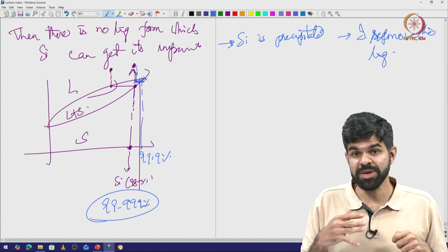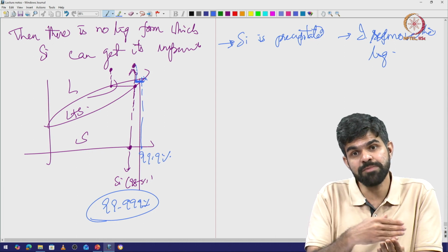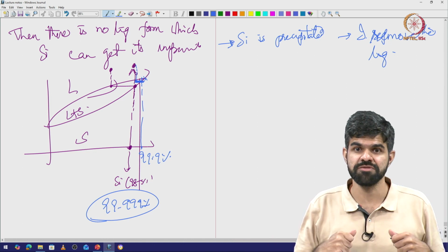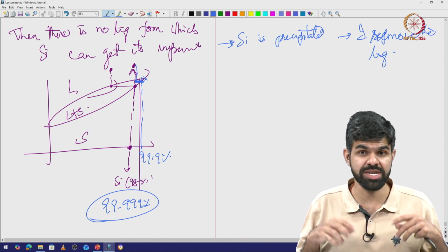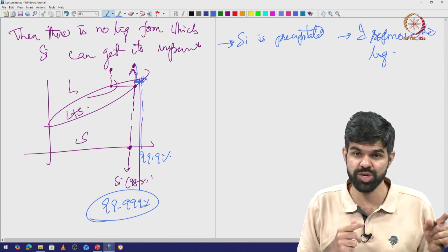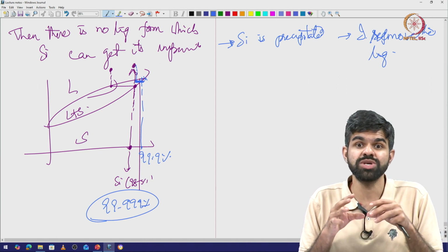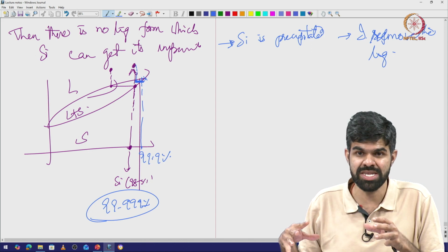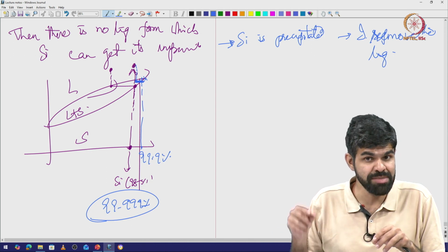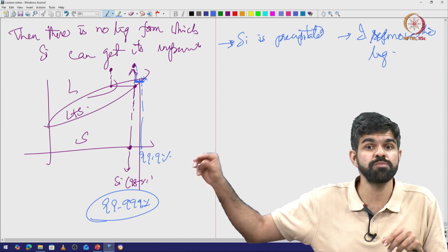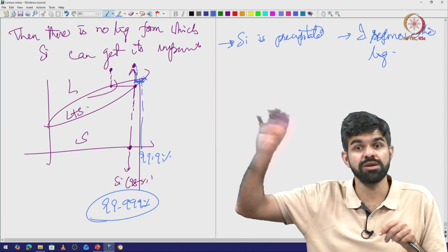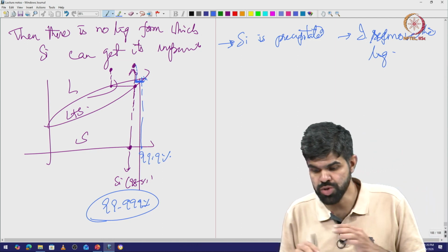But for sweeping out the floor, it is not that I sweep and then put the fan on. If I put the fan on, again the dust is sort of redistributed. So, that is not what I should be doing. In the first strategy I was doing that, but actually I should separate out the liquid from solid, so that this liquid solid equilibrium does not exist, and once that does not exist, then the solid becomes pure, more pure, more pure. So, then I keep on cycling it again and again, so that I keep on removing the impurities. Okay. Now, how do you do this?